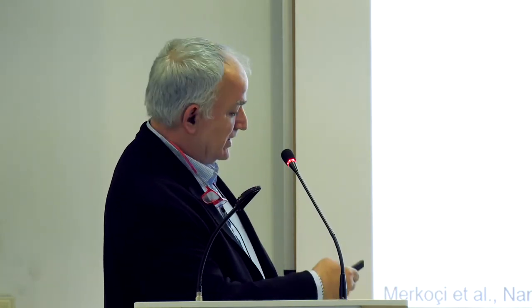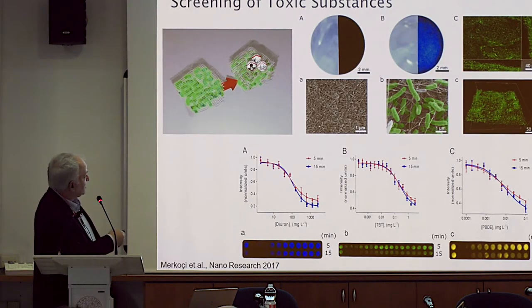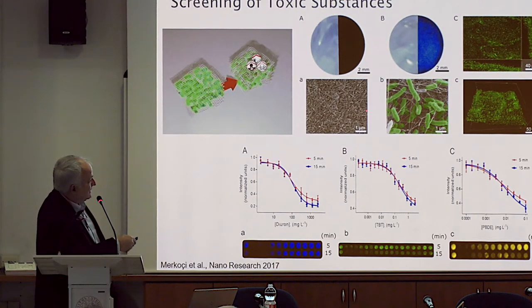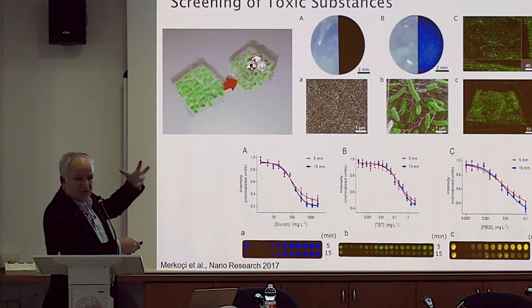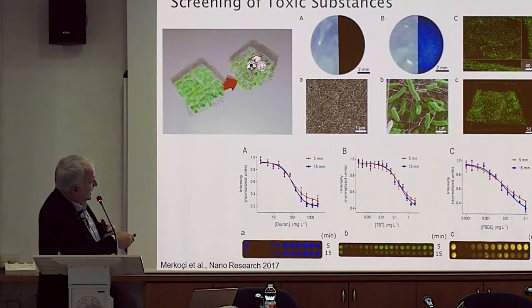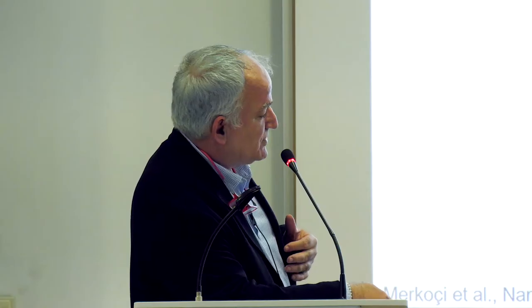So for smart packaging, which is of interest for safety and security, or even detection of toxicity of water by using some bacteria. There are some well-known luminescent bacteria that change the color in presence of some contaminants, for example pesticides. So what we did is we integrated this bacteria, which is really very stable, with a very nice luminescence inside this paper, and we saw how the change of the luminescence of this bacteria was happening in contact with different kinds of toxic compounds. So in this way we are able to detect these contaminants.